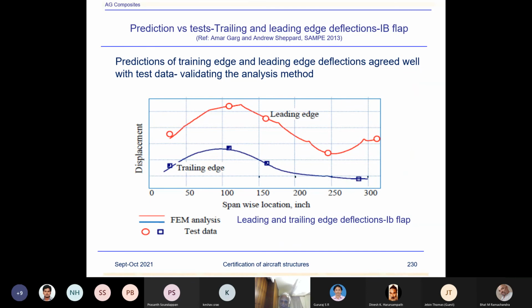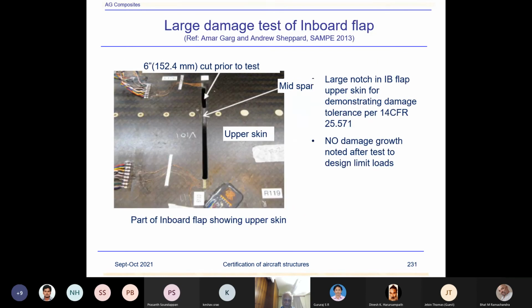So I was discussing this, and essentially what I said is that the analysis confidently showed that the test matched the analysis data. Another thing I said, in order to show the visible damage, a large notch was created in the IB flap. This is only showing a part of the inboard flap showing the upper skin. As you can see, a large notch right up to the middle spar from the trailing edge, in the flap upper skin, for demonstrating damage tolerance compliance. No damage growth was noted after the test to design limit. So it was tested to limit load carrying capability with no damage growth.